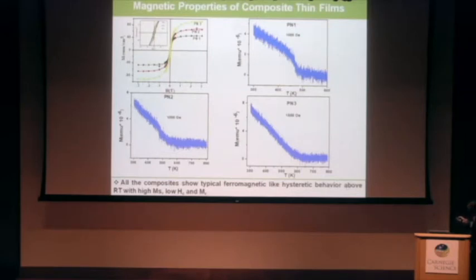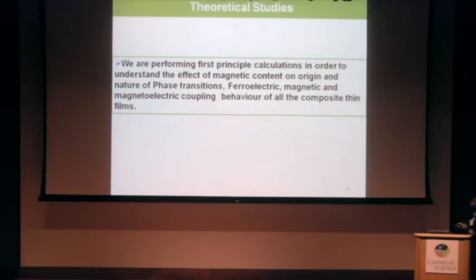And in the PN1 and PN2 cases, the magnetic phase transition is observed around the ferroelectric phase transition temperature, plus or minus 10 or 20 degrees Celsius. And this is the PN3 one, where we are getting around 550 Kelvin. Here, all the composites show typical ferromagnetic-like hysteresis behavior above room temperature, with high saturation magnetization, low coercive field, and low remnant magnetization. And we are also performing some first principles calculations